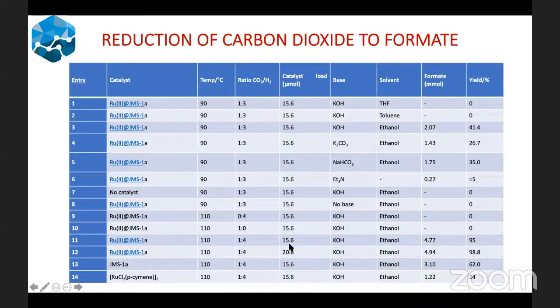And then entry number 11 and number 12 looks at the effect of the catalyst load. As you increase the catalyst load, as you can see here, the yield of the formate that is formed also increases, which confirms that this reaction is first order. We also checked the activity of the activated MOF. This is the one which does not contain your ruthenium complex inside the MOF.